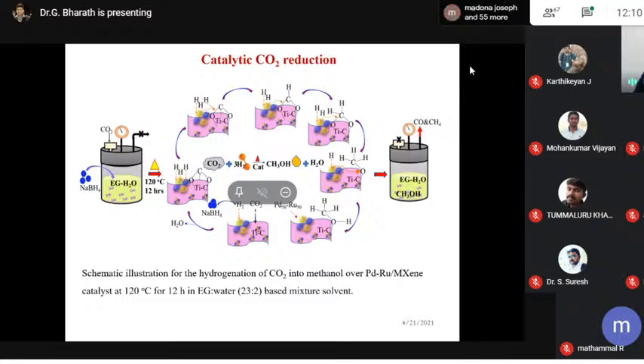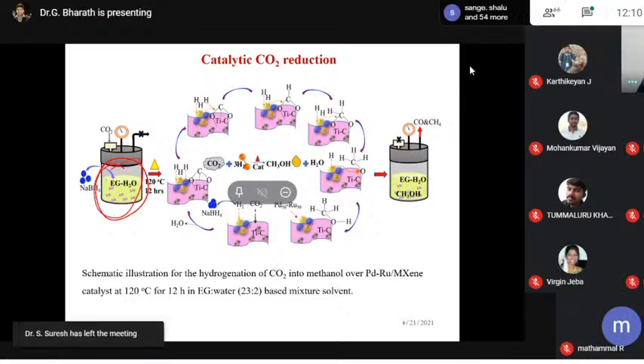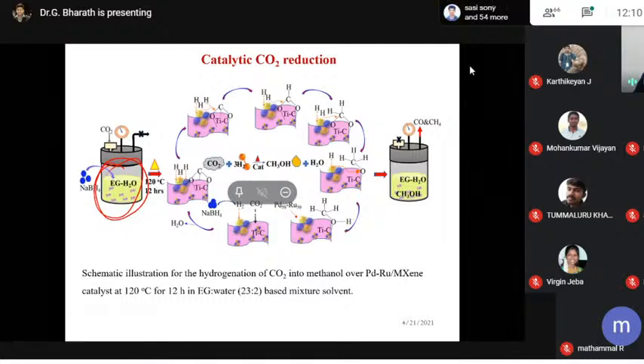Here we developed an integrated system with ethylene glycol. If you see ethylene glycol and H2O, this is the best capturing solvent. It easily captures CO2. When we pass CO2 into this hydrogenation chamber, the CO2 is easily captured by ethylene glycol, and we have already dispersed our material in the solvent. Our materials are inside, and CO2 molecules are also inside the ethylene glycol and H2O. This is the complete solvent.